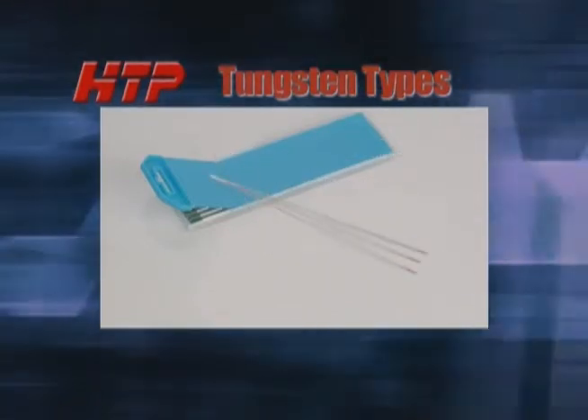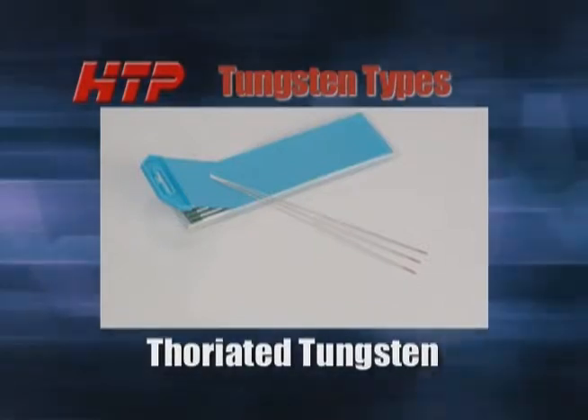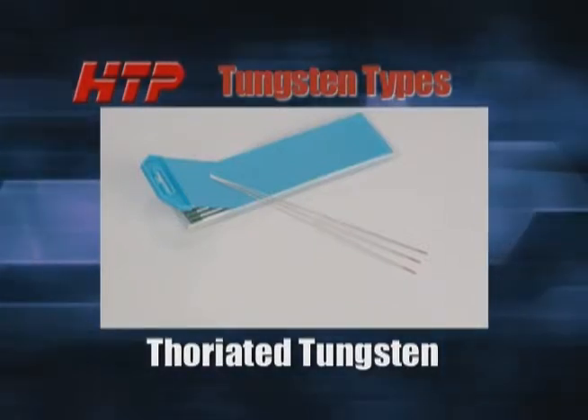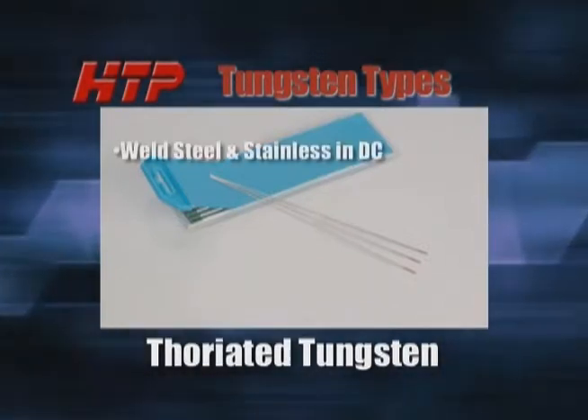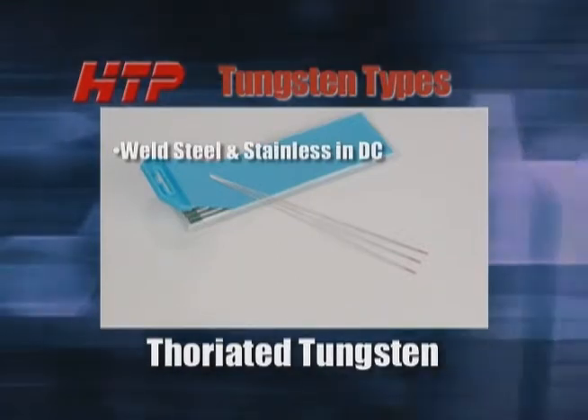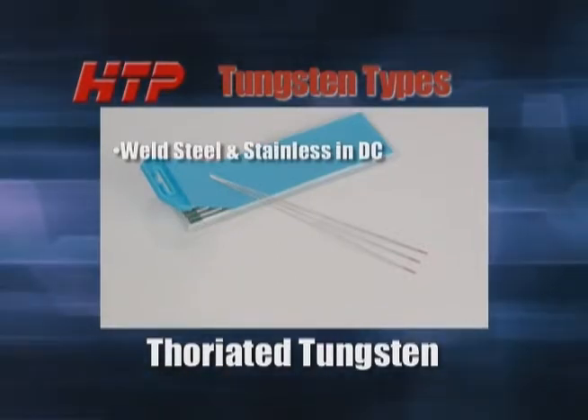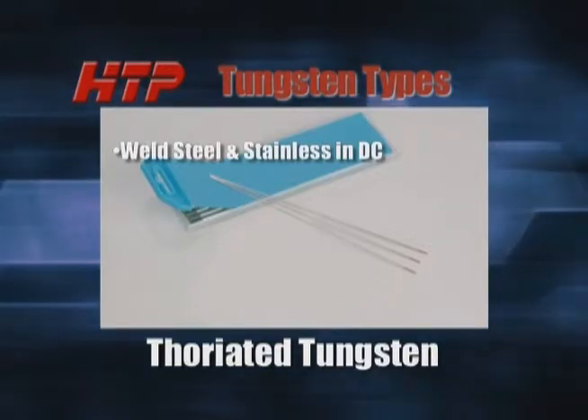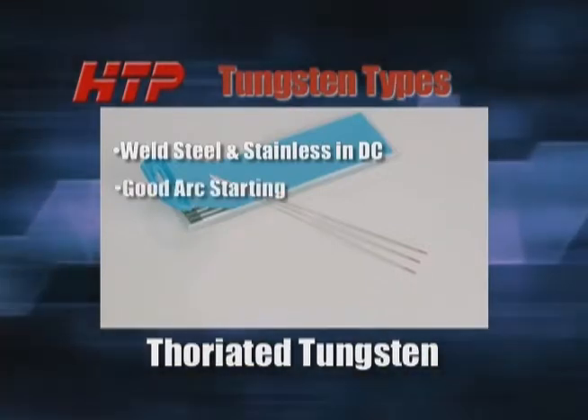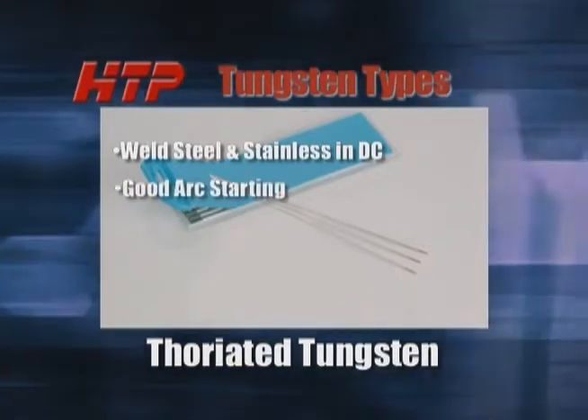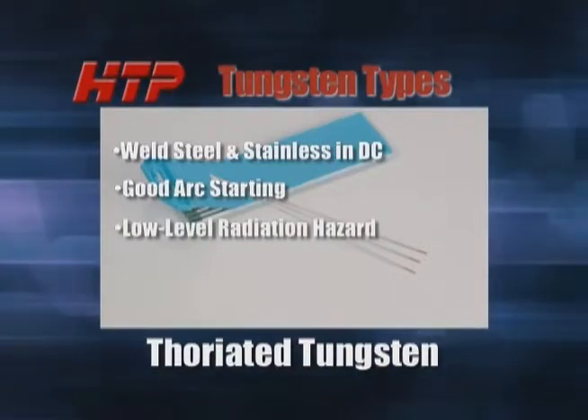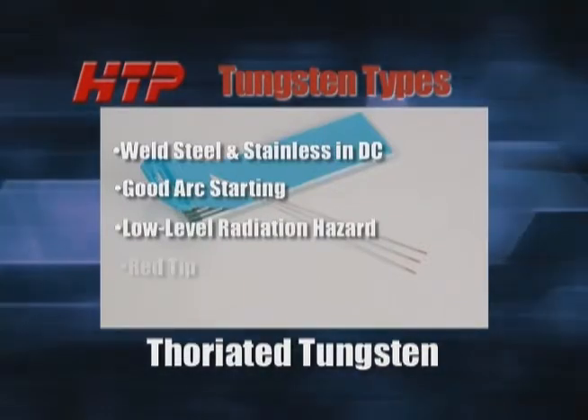2% thoriated tungsten is the most common tungsten used today. It is generally used in the DC mode for welding steel and stainless steel. It provides excellent resistance from weld pool contamination and provides good arc starting capabilities. It does have a very low level radiation hazard, designated by a red tip.